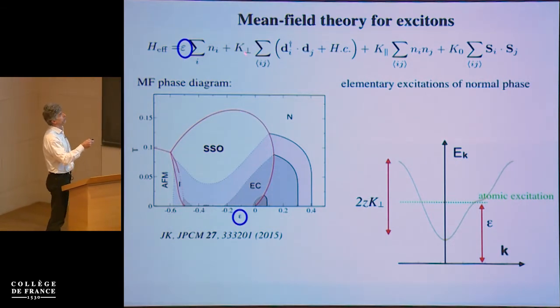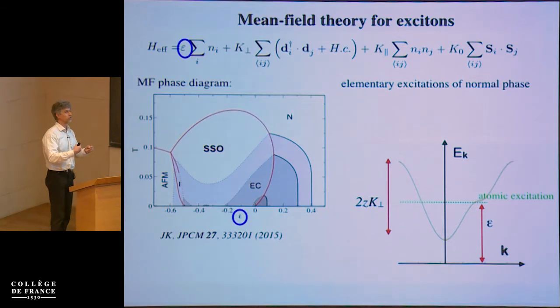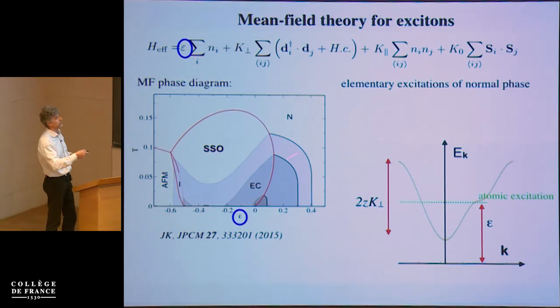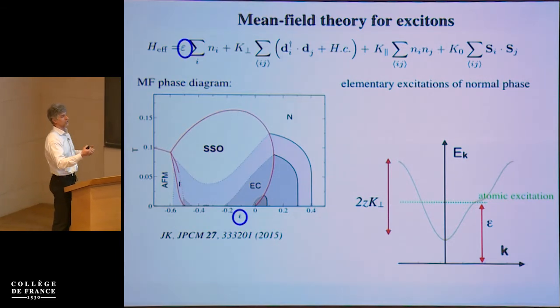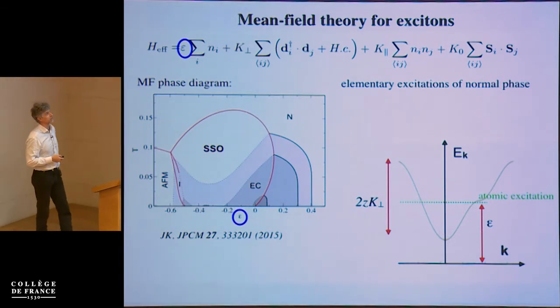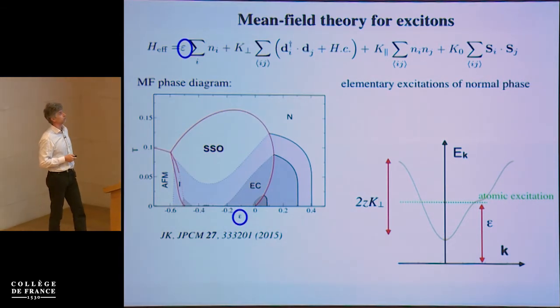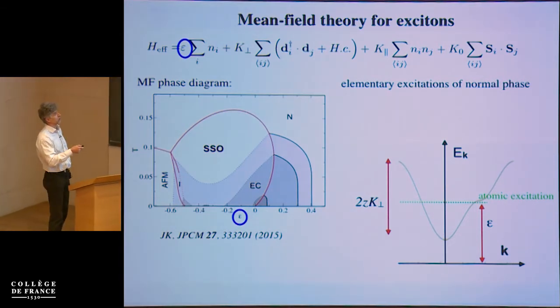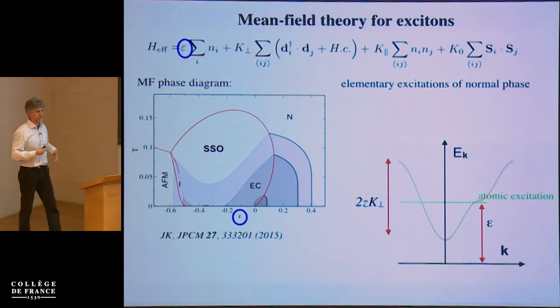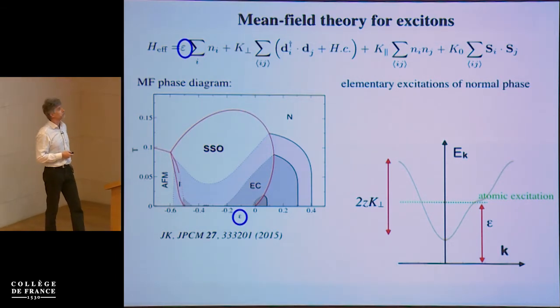Then we have a term which describes the hopping of the bosons on the lattice. Then we have a term where we have the nearest neighbor repulsion between the bosons, which does not depend on their spin. And then we have a term which is spin exchange between these bosons, kind of the standard super exchange term. Such a model can be rather accurately described by a simple mean field theory.